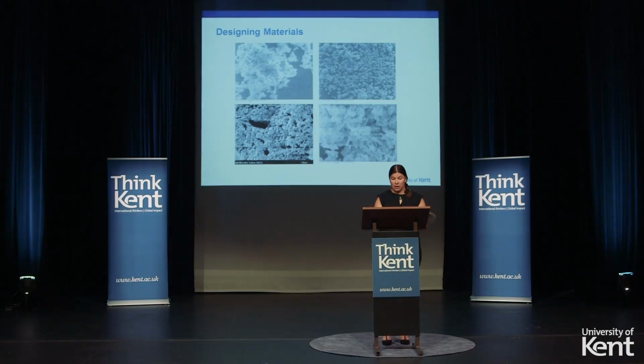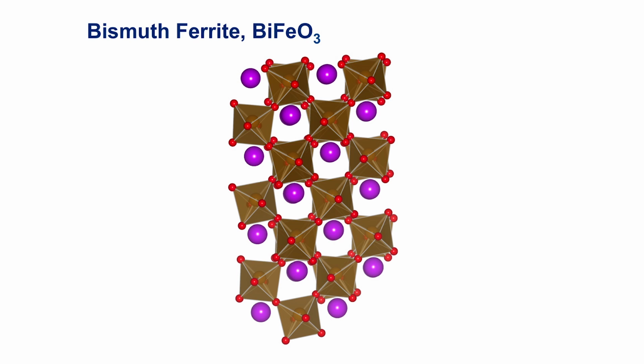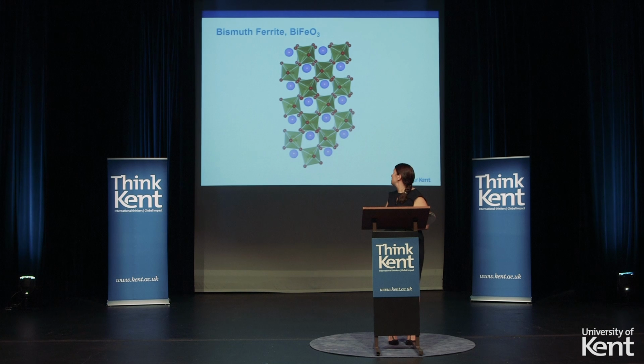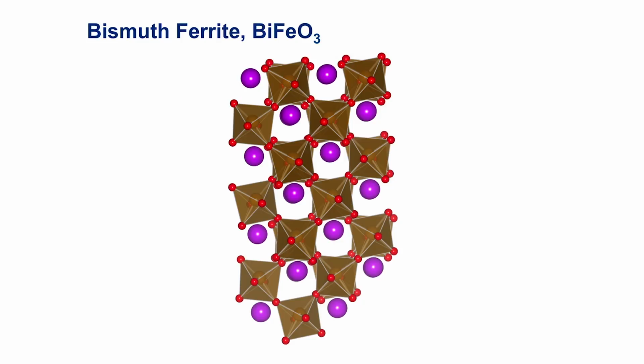Our work centres on the perovskite bismuth ferrite. Bismuth ferrite is arguably the most important multiferroic. This is because it's perhaps the only multiferroic material that shows both room temperature electric and magnetic ordering. The magnetism arises from the unpaired electrons on the iron ion. However, it doesn't order nicely in a ferromagnetic way as we would like. It orders in a much more complex magnetic arrangement. If we look here, we can see the bismuth, the purple ions. It has a lone pair, and this forces it to sit off-center in this perovskite cavity. This causes the formation of a dipole moment, and this is the origin of the ferroelectricity.